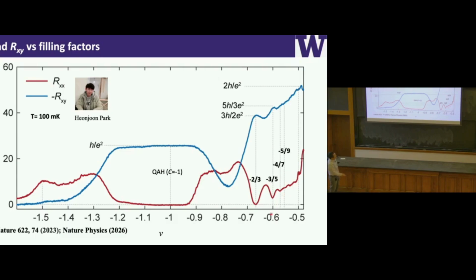And these smaller filling states are not fully developed, partially due to a small gap, partially due to bad contacts, actually. Yeah. Okay, so at least we observe a Jain sequence of these FCI states. And we can also measure Rxy as a function of magnetic field, as I show here, right? The blue curve is Rxy, with the horizontal axis sweeping the magnetic field forward and backward. We can clearly see that Rxy is quantized at zero magnetic field, right? And with vanishing Rxx. So that's the demonstration of the fractional quantum anomalous Hall effect.